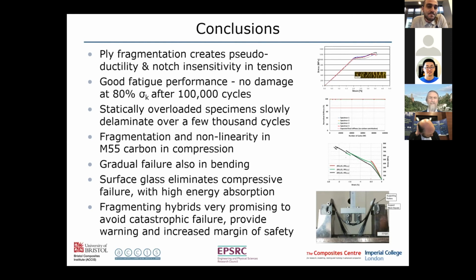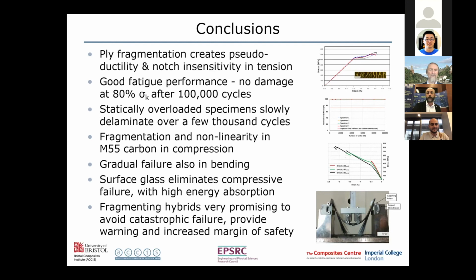I don't think it affected this case because the specimens are pretty stiff and the strain gauge and the cable are not very significant. But it's a good point that you do need to worry about this. I remember when we did work on just resin samples, the strain gauge made quite a significant difference to the stiffness of the specimen. But for these composites, I don't think it does. We've used video extensometers usually as well as strain gauges, and we get very similar results.